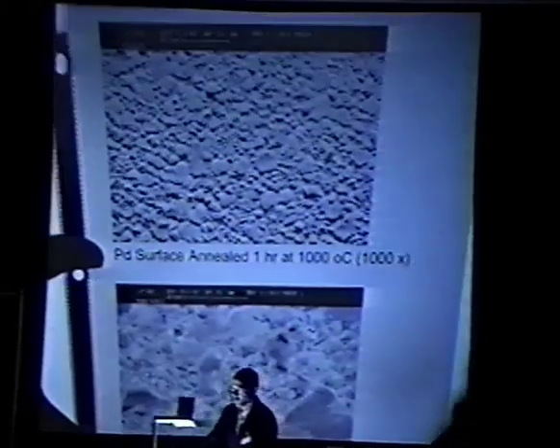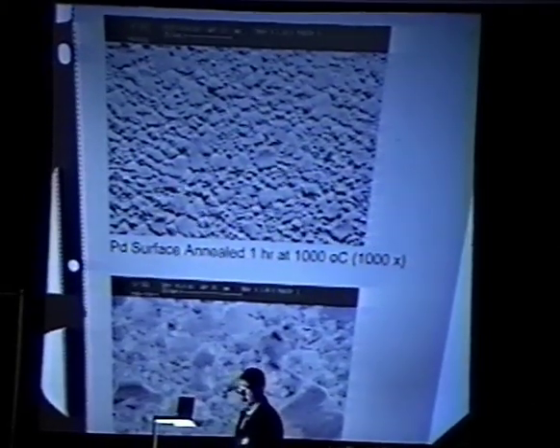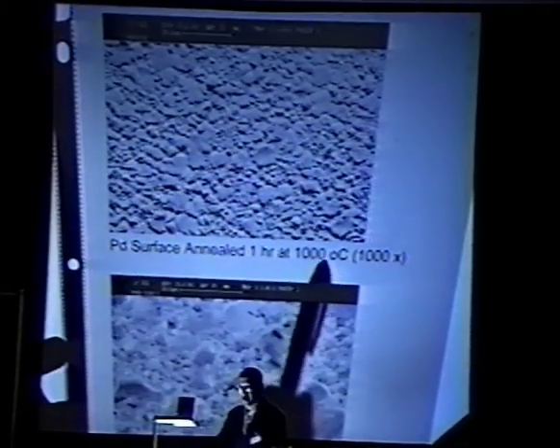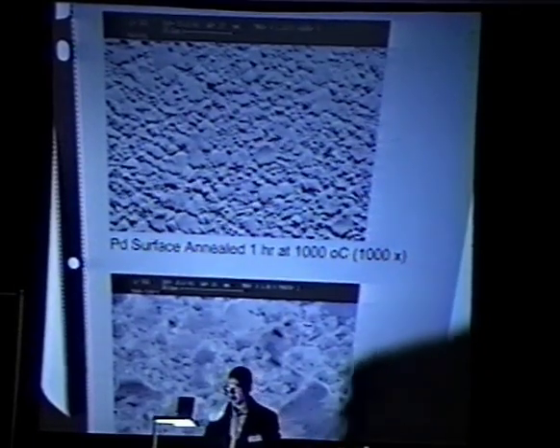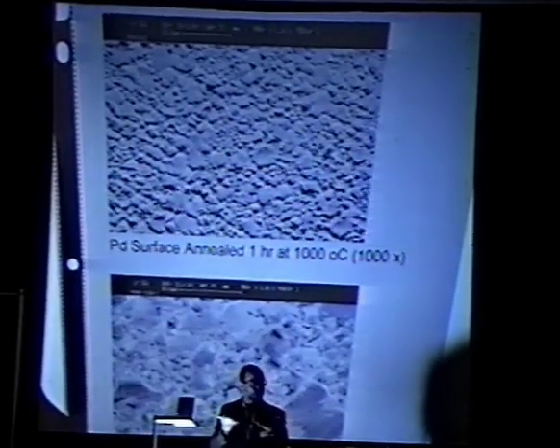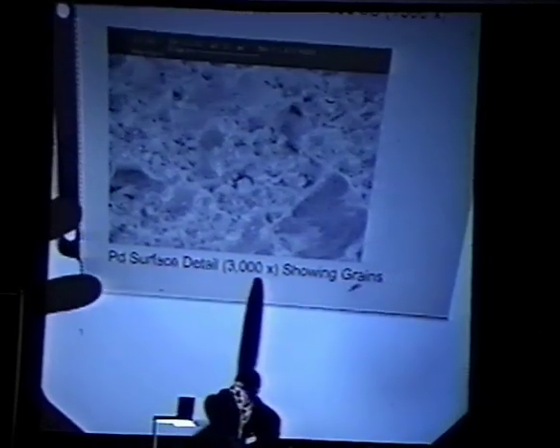That one was for an as-deposited film, which means there was no annealing. I also did a few runs with annealed palladium. This is a typical one that was annealed for an hour at 1,000 degrees centigrade. Again, this is a much larger scale, 20 microns here. So the grains are starting to relax and grow. You're seeing the equiaxed grain structure. This is again just one showing a little bit more magnification.